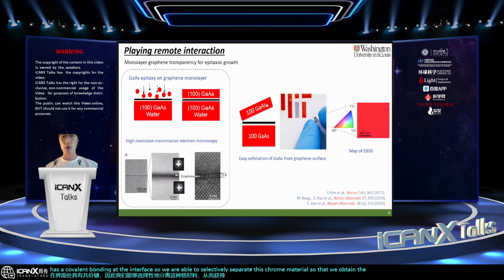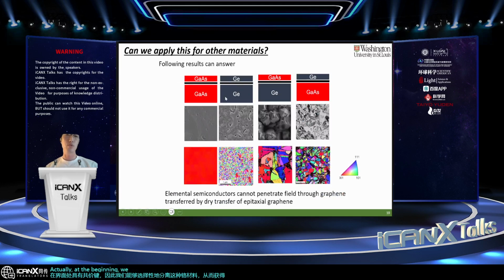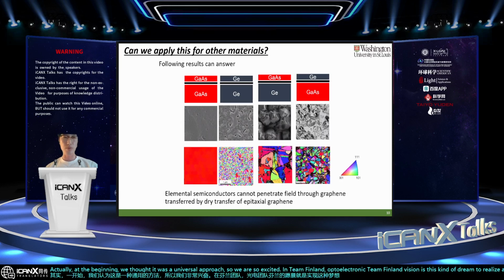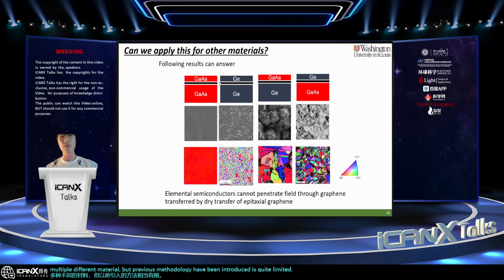Actually, at the beginning we thought it was a universal approach, so we were so excited. In the optoelectronic thin film region, it is kind of a dream to realize a very thin nanomembrane with multiple different materials. But previously introduced methodologies are quite limited because of some fundamental reasons. So we thought this may be the universal approach, and we were so excited. So we tried to apply this to other material systems. But when we tried germanium, it was not really successful.